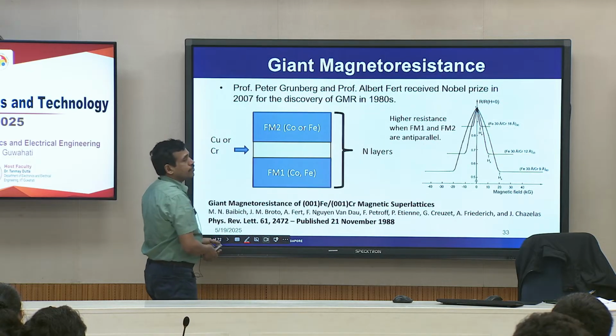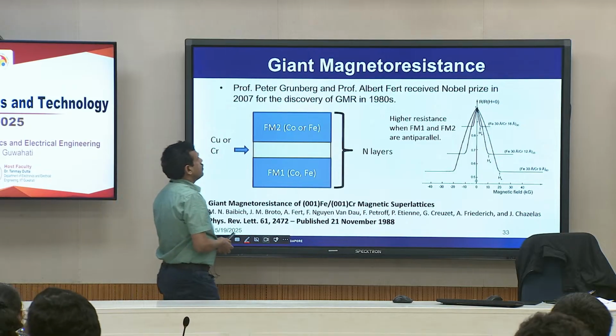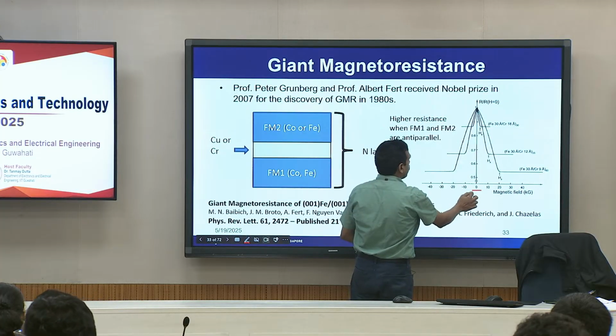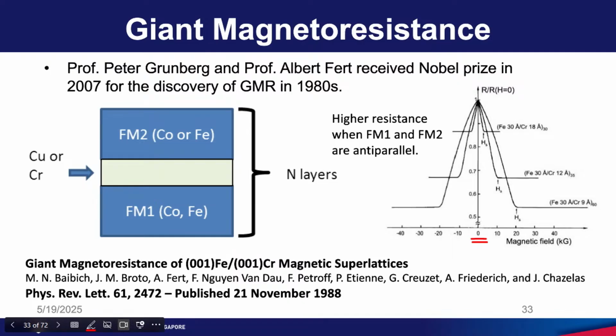This group, as well as the group of Peter Grunberg, explained this result: when you do not apply any magnetic field, you observe high resistance. This is because at this particular field, the magnetization of the two neighboring ferromagnetic layers are anti-parallel. For example, if the magnetization of this layer is pointing towards right, then the magnetization of the neighboring layer is pointing towards left, and so on. If you have 60 layers, one points right, one points left, then right, left, and so on. So, the neighboring magnetizations are anti-parallel in the absence of a magnetic field. This is the situation when the magnetic field is 0.